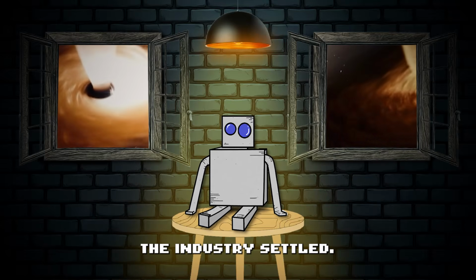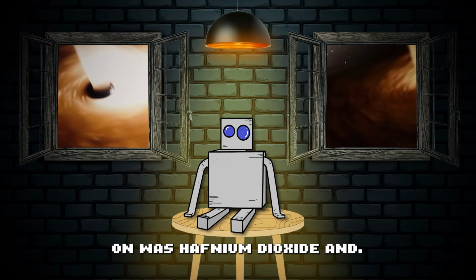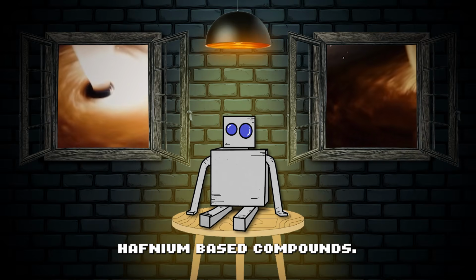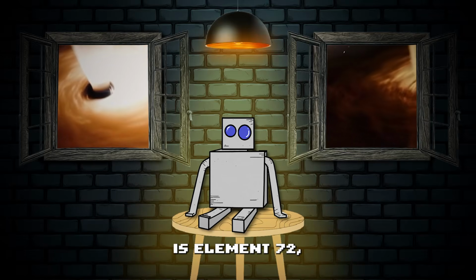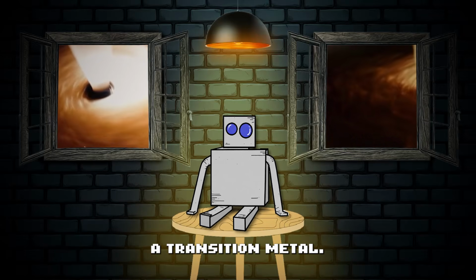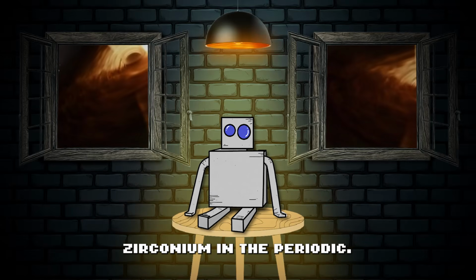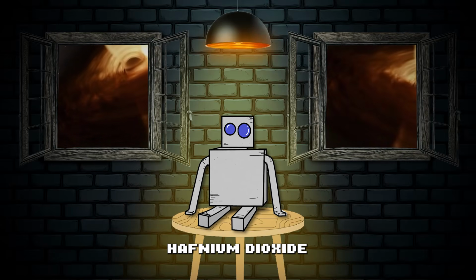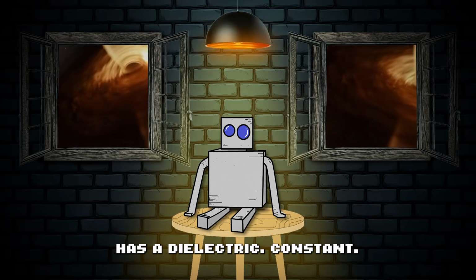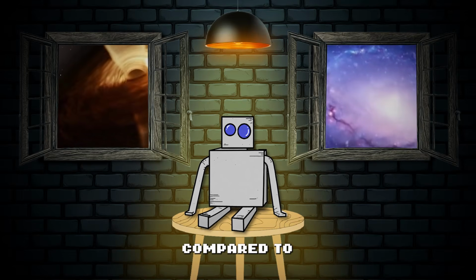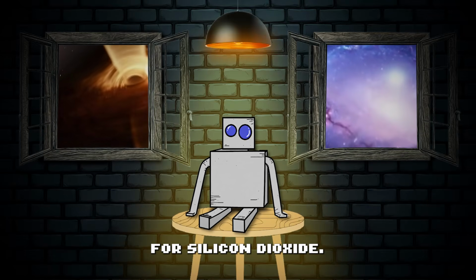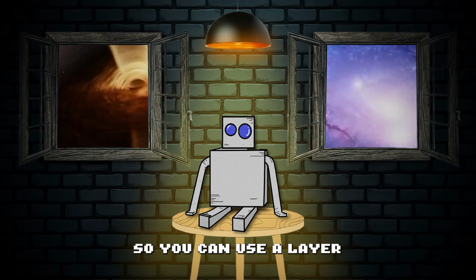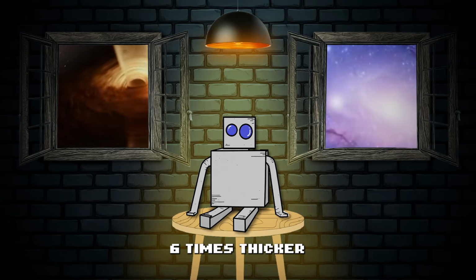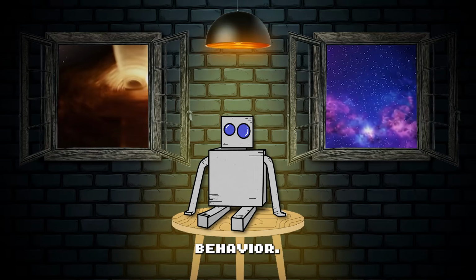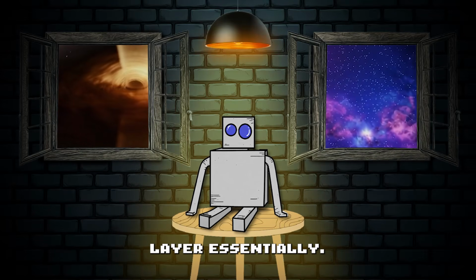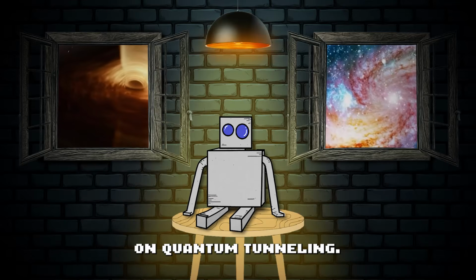The material the industry settled on was hafnium dioxide and closely related hafnium-based compounds. Hafnium is element 72, a transition metal. It sits right below zirconium in the periodic table. Hafnium dioxide has a dielectric constant of roughly 20 to 25, compared to about 3.9 for silicon dioxide. So you can use a layer that's physically 5 or 6 times thicker and get the same electrical behavior. That thicker layer essentially slams the door on quantum tunneling.